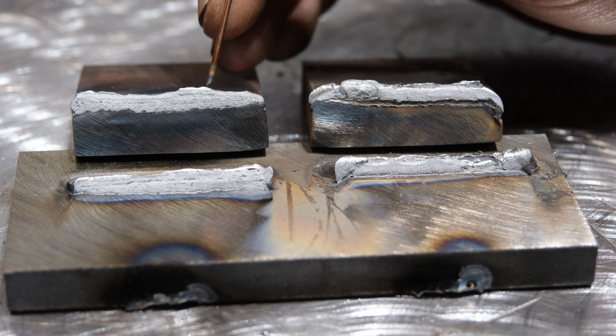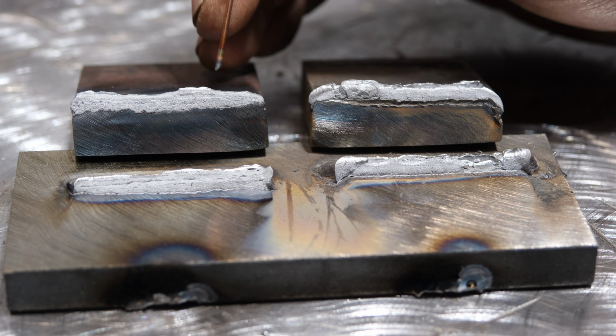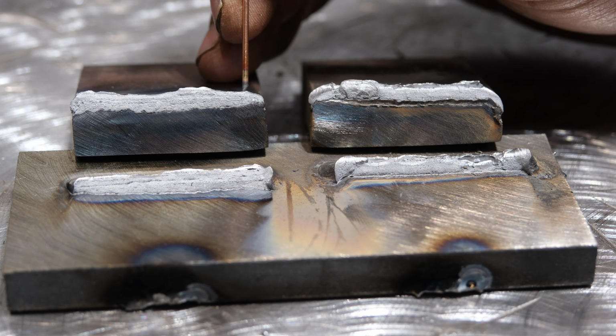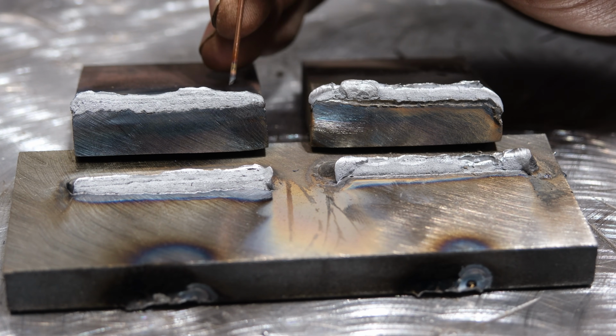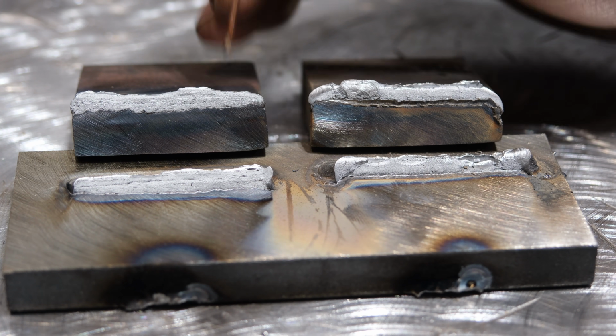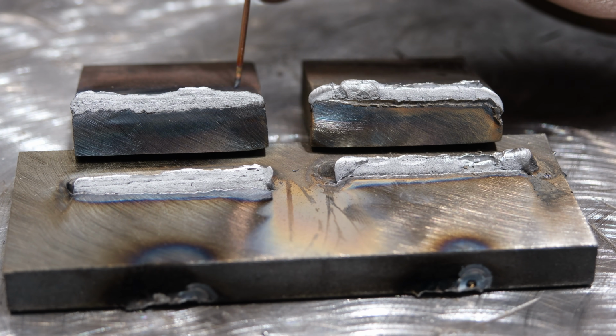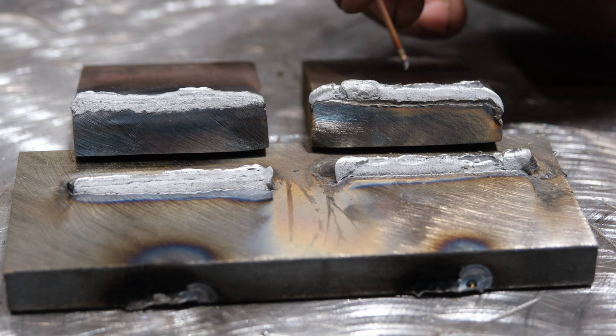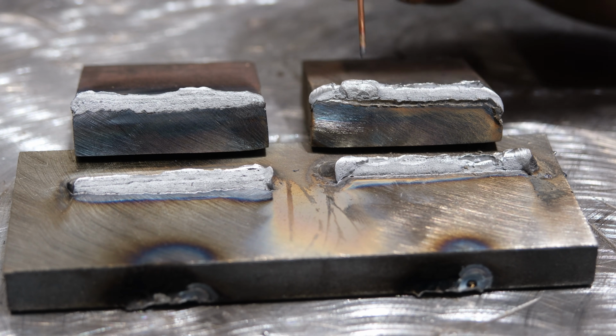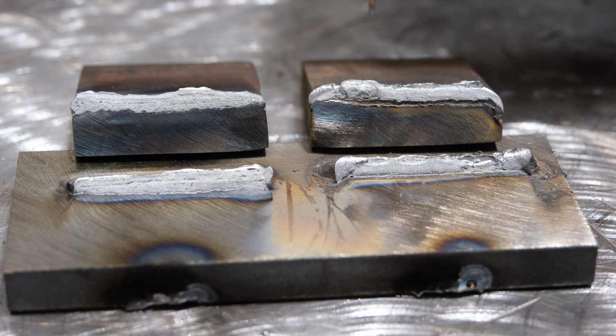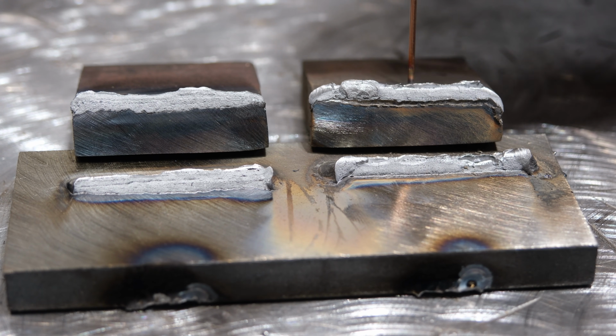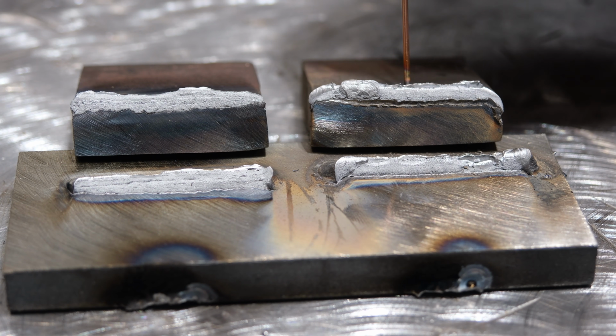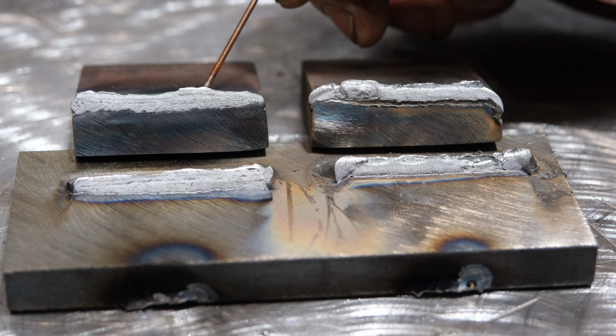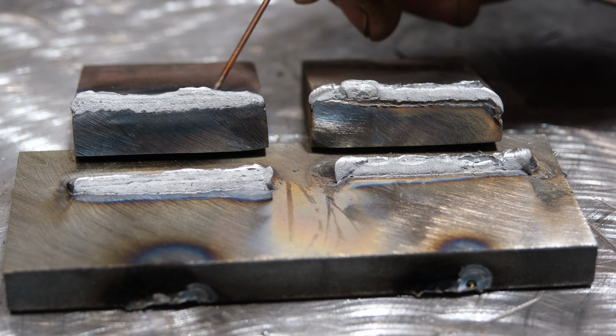And keep in mind, this TIG weld I welded at about 190 amps, which is higher than I would have generally done. I just did it because these plates were somewhat cold. This would be capable of being welded at about 165 amps with no problem on this 1/2 inch thick steel. I ran the 7018 2.4 millimeter, 3/32nd rod at about 95 or 92 amps. So the cool thing is yes, depending on welder, you could weld this 1/2 inch plate pretty successfully with a fairly low powered, 120, 130 amp stick welder, which is good. But the TIG welder, I mean, a 160 amp TIG welder, you can get for like, I don't know, $400 or $500, and you could tackle this.